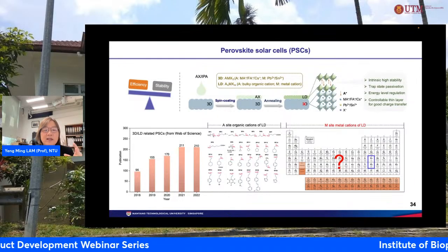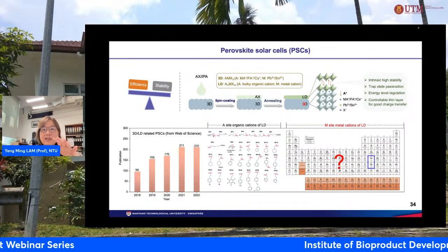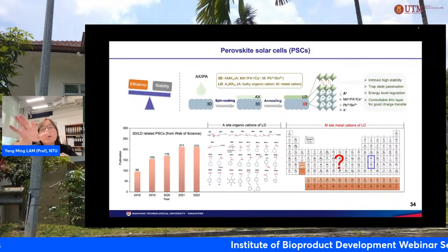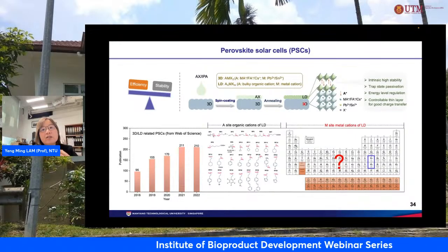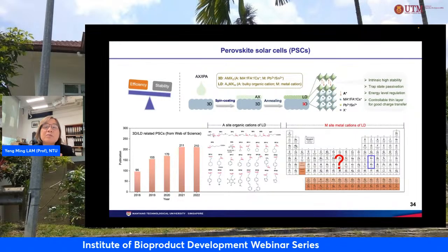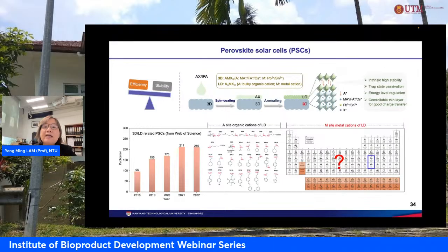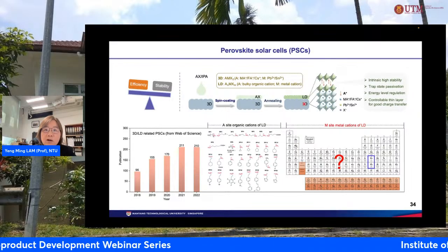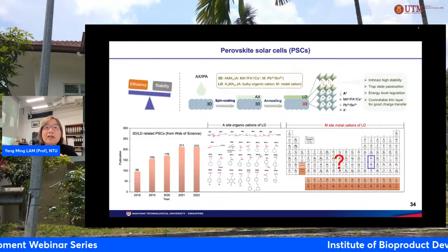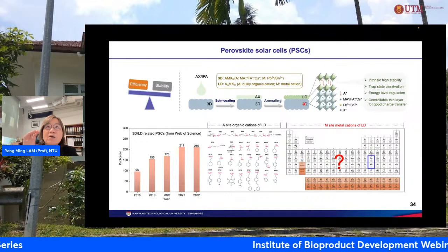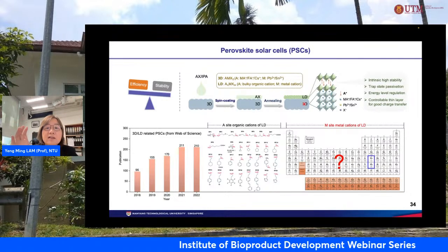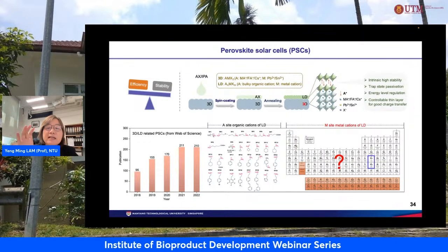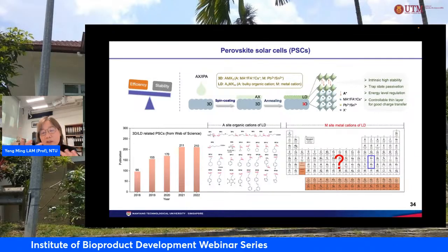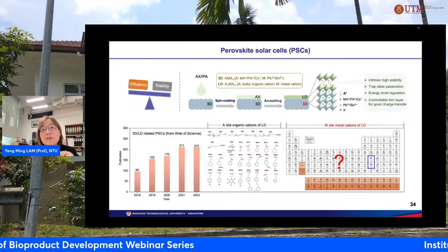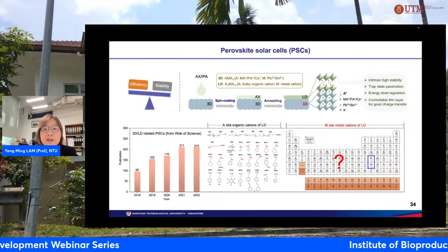So we have a perovskite, which is the base material, and then on top of it we put a low dimensional material. Generally, this low dimensional material can help to protect this three-dimensional material because the low dimensional material has a longer organic cation tail. A longer cation tail means that it becomes more hydrophobic. It will defend the base material against any moisture.